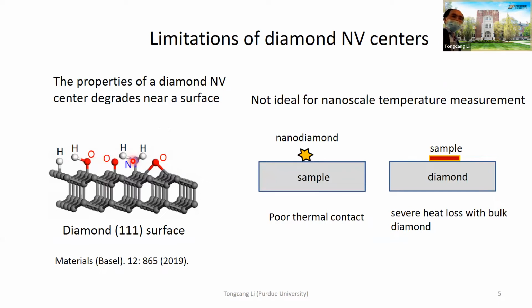Another thing is that diamond is a very good thermal conductor. In some sense, that is not good for measuring temperature. For example, if I use a nanodiamond to measure the temperature of a sample, then the contact is pretty poor.